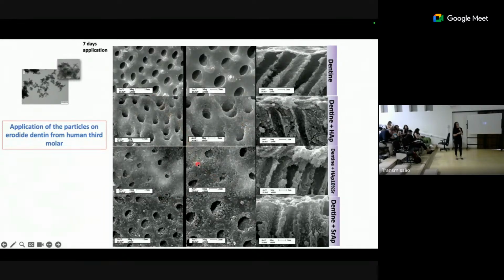And if you see here, the particles were able to deposit at the surface of dentin. In special, the particles containing strontium coated the surface much better compared to hydroxyapatite. Okay, but if in Sensodyne Rapid Relief we already have strontium, what are we doing to put in another kind of strontium? We should realize that strontium acetate is a soluble form of strontium. So if you have used Sensodyne Rapid Relief, as soon as you stop brushing the teeth, 2 days after, you have the hypersensitivity again. So it's not a persistent treatment. So the idea here was